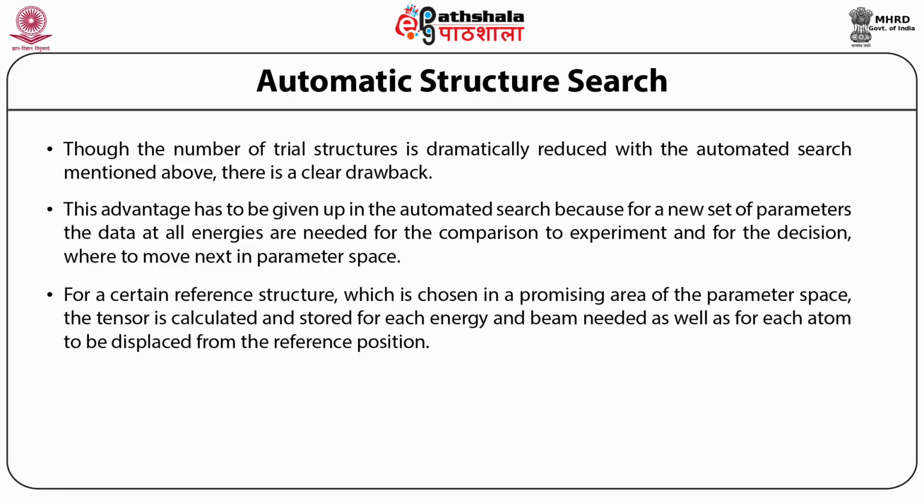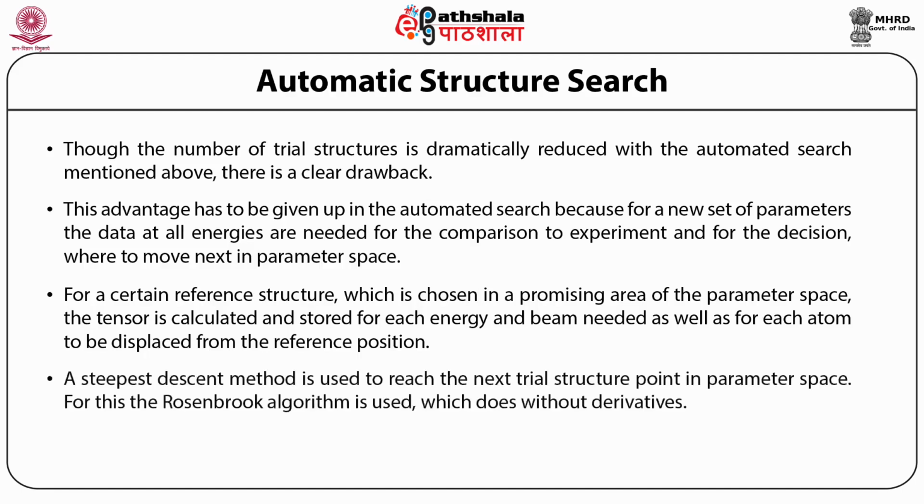The tensor is calculated and stored for each energy and beam needed, as well as for each atom to be displaced from the reference position. The intensities for a trial structure are calculated and compared to experiment by the Pendry R factor. A steepest descent method is used to reach the next trial structure point in parameter space. For this, the Rosenbrock algorithm is used, which does without derivatives. The procedure described is iterated until an R factor minimum is reached.